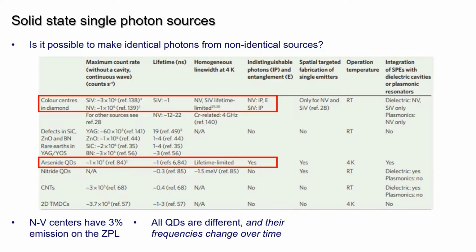And so from color centers in diamonds, particularly nitrogen vacancy centers, and with gallium arsenide quantum dots, they've demonstrated what's called transform-limited lifetimes. What does that mean? Well, it means that the frequency of light which is released is the exact same frequency of light you would expect if there were nothing else. If there were no crystal, no phonons messing with it. And you can actually achieve that even in a crystal as long as you cool it cold enough. So this is already quite remarkable.